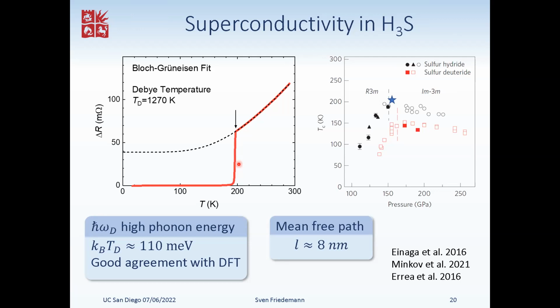Hirsch has criticized the work of Ranga Dias on the carbonaceous sulfur hydride, which was published in Nature 2020. He's criticized that much more, and there is some reason to that, because if you look at the resolution of what they call the zero resistance state, it's more of the order of a microohm centimeter. So their measurements would be consistent with something going from a bad metal to a good metal. Whereas Eremets' work and other work on the hydrides indicates that it would have to be an extraordinarily good metal that we go to.